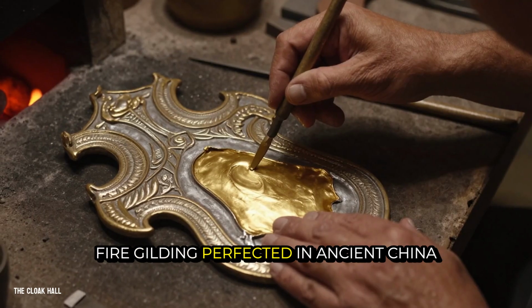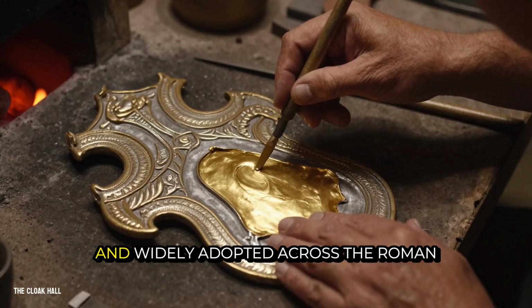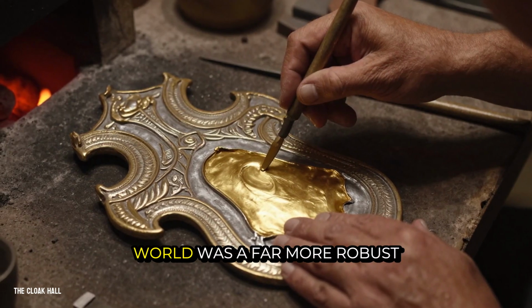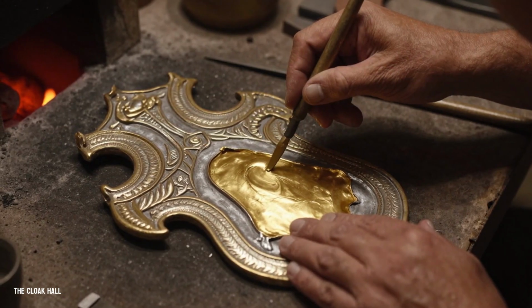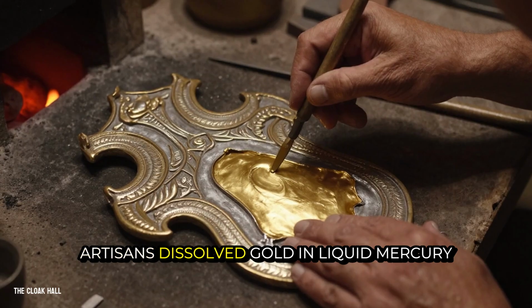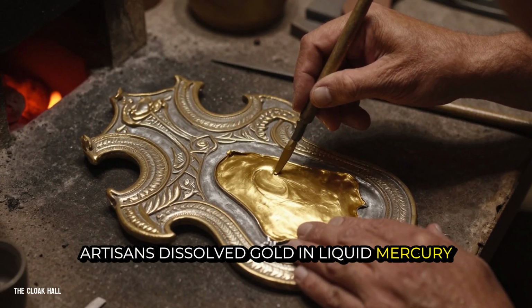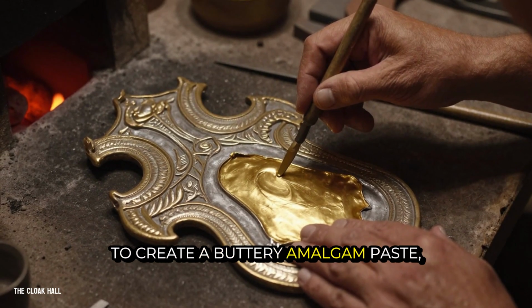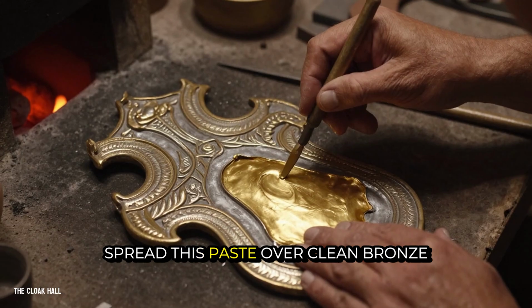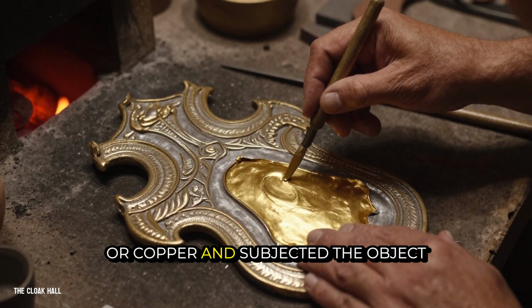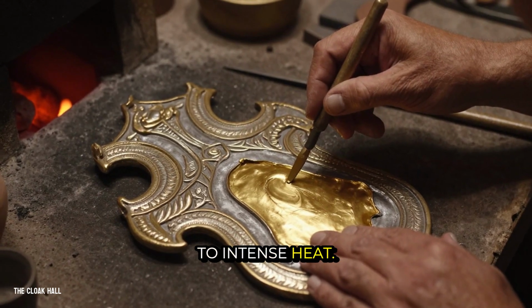Fire gilding, perfected in ancient China and widely adopted across the Roman world, was a far more robust chemical method. Artisans dissolved gold in liquid mercury to create a buttery amalgam paste, spread this paste over clean bronze or copper, and subjected the object to intense heat.